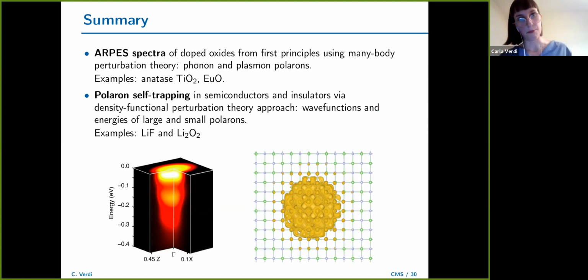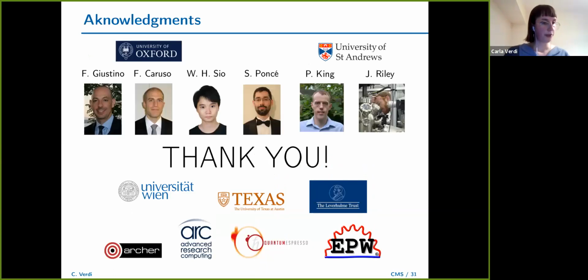And this approach has advantages and drawbacks. One drawback is that, as we said, we weren't really able to describe polaron self-trapping. And so I introduced to you a new theory to describe polarons via, let's say, a density functional perturbation theory approach, which doesn't use supercells and really allows us to get the wave function and energies of both large and small polarons.